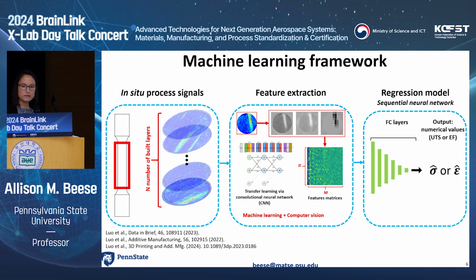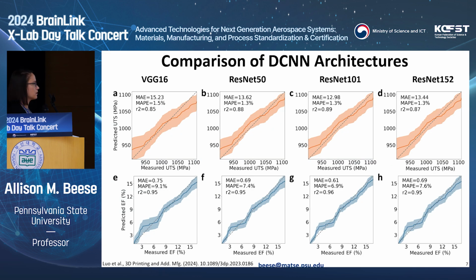And so what this allows us to do then is I'm showing a bunch of plots here. As we go, the top row is our predictions of ultimate tensile strength versus measured, and the bottom is predictions of ductility versus measured. And from left to right, these are just increasing complexities in DCNN architectures. And what you can see here is that the solid line, each of these represents our average predicted ultimate tensile strength or ductility as a function of measured. And the bands represent the scatter because each of those samples has 500 layers of data.